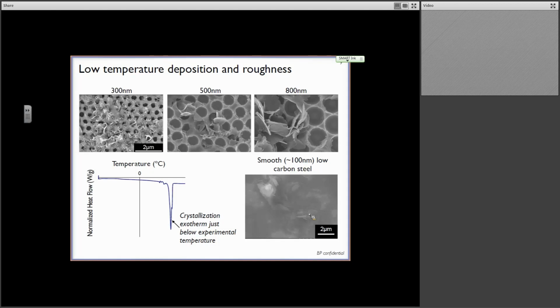But I want to further suggest that we do see these sorts of plate-like structures on our carbon steels, right? So this isn't necessarily just an effect of our unique surfaces here, in terms of chemistry at least. These plates are actually a unique property of the model asphaltene molecule that we're working with. If we look at this DSC data here, we have this crystallization exotherm that happens just below our experimental temperature, and we believe that's why we see these plates, whereas we don't see this nice morphology at lower temperatures if we do the same tests at room temperature.